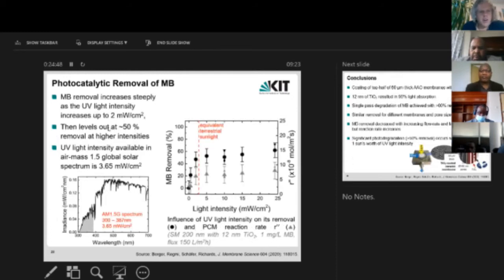If we look at the photocatalytic removal of methylene blue as a function of light intensity, we see quite an interesting trend. There's a very steep rise in the performance up to about 2 milliwatts per centimeter squared. And then after that, it's relatively flat out to 25 milliwatts per centimeter squared. So obviously the availability of light is not our main problem here. It's not limiting our performance.